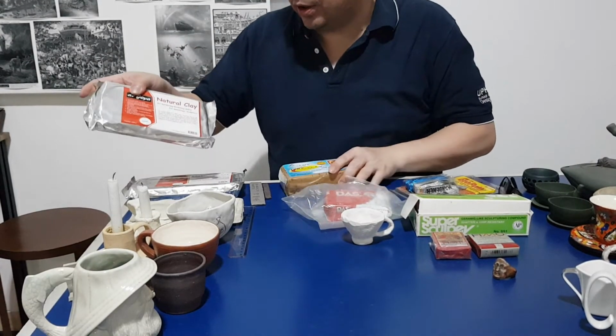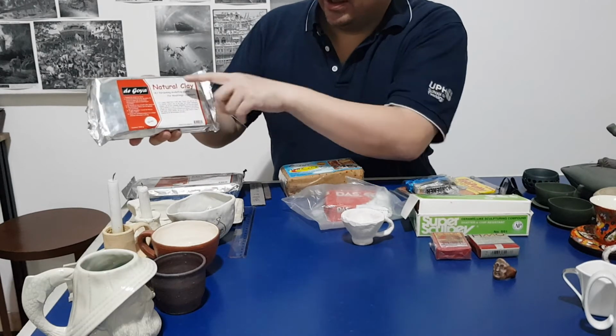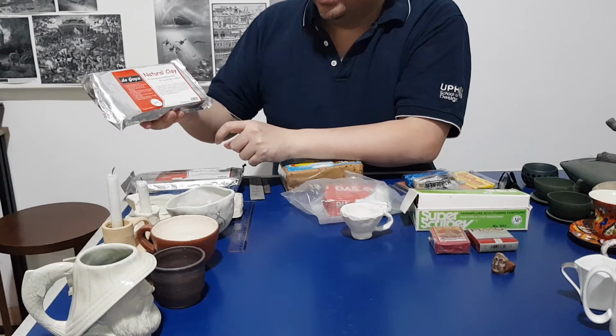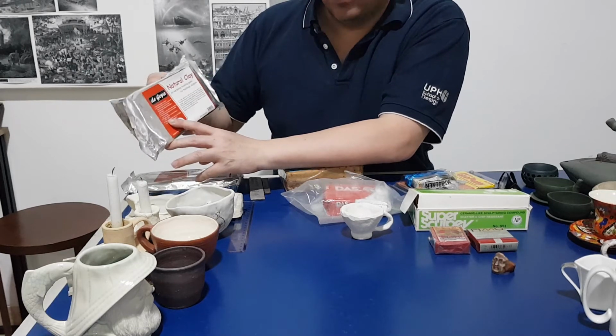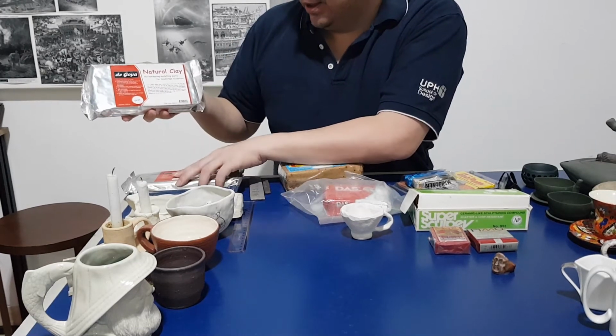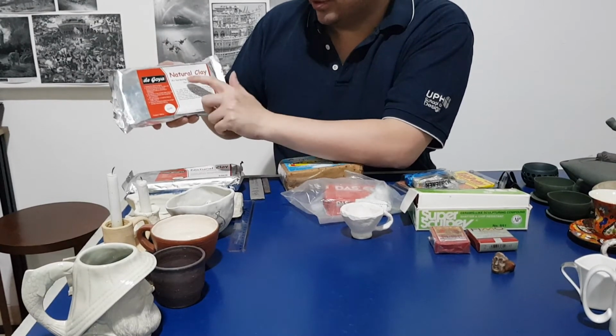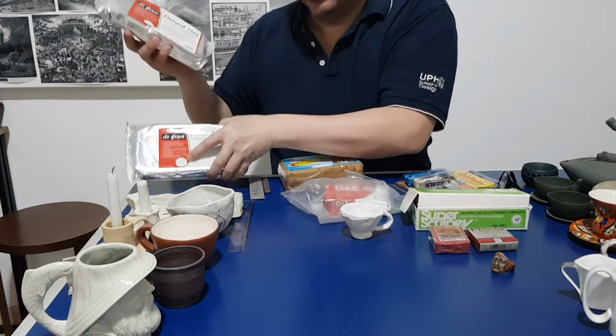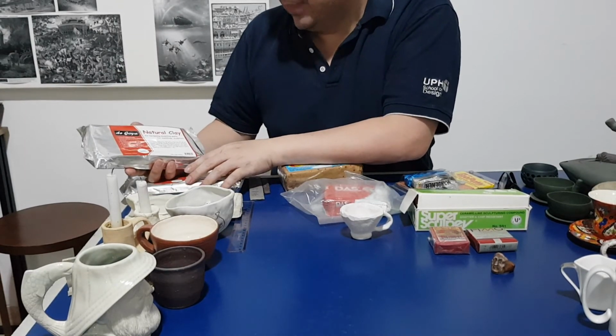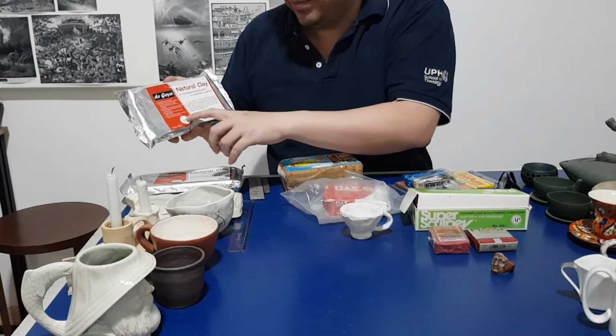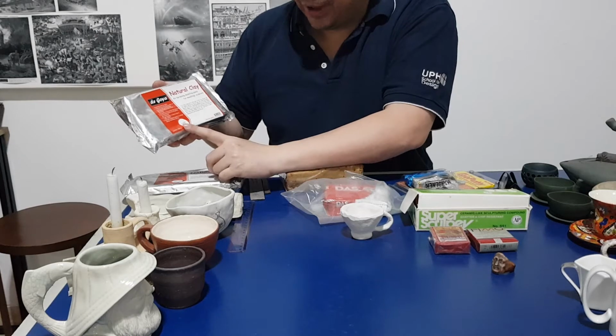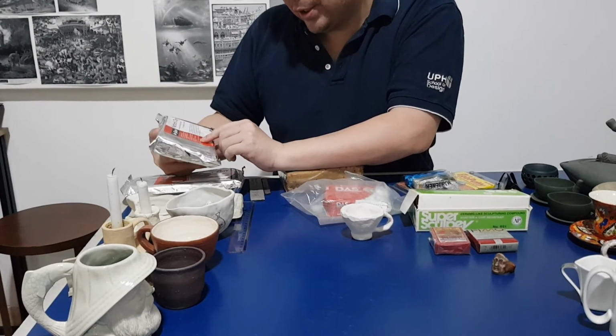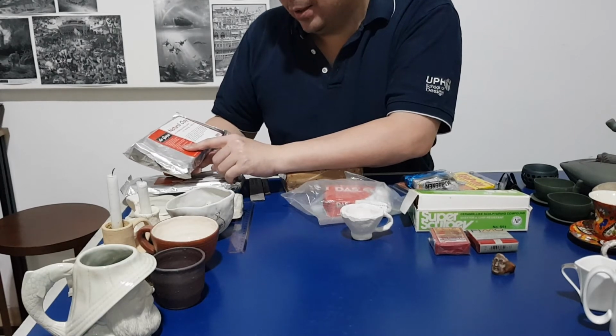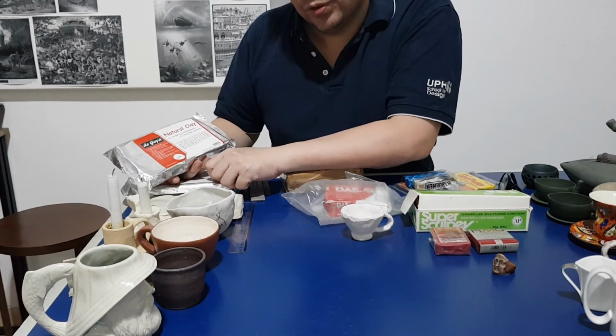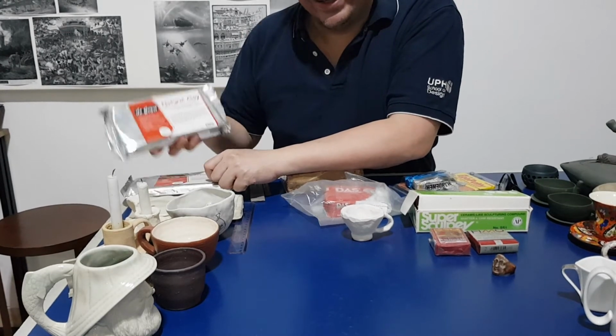There are other brands which are not as common, not easy to find, like de Goya natural clay. This you can get in some of the specialty art stores, and it says this one can be fired to 1,000 to 1,200 degrees Celsius. They come in 3 colors from what I know. So natural clay, gray, white, and there is another one that's terracotta color. But again, it's not as easy to find, and sometimes you have to test them, because most of these clays, sometimes the instruction says it goes to 1,200, but I did fire to my kiln, usually I fire to 1,100 degrees Celsius, and these clays actually started melting.